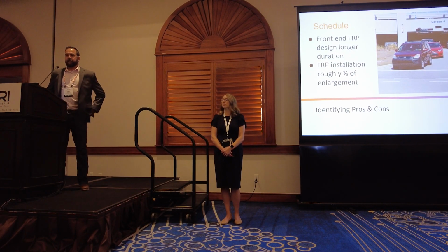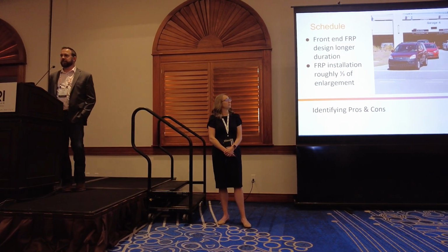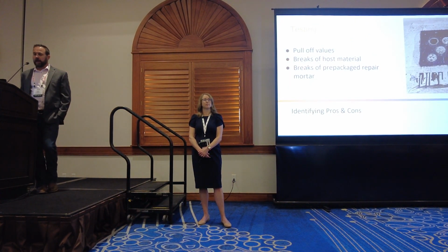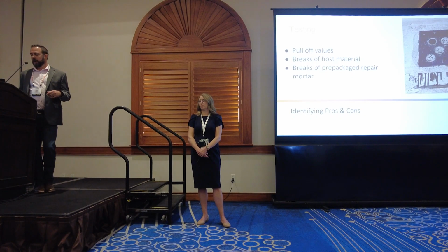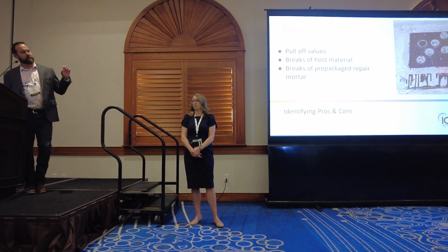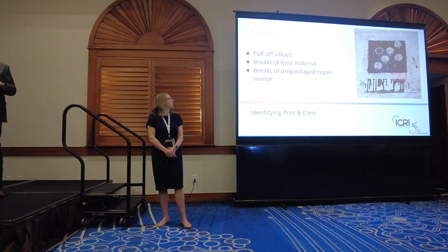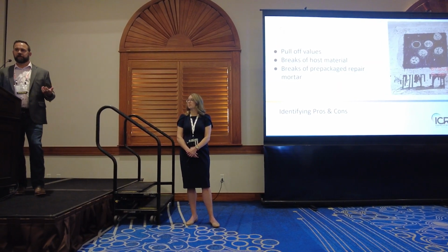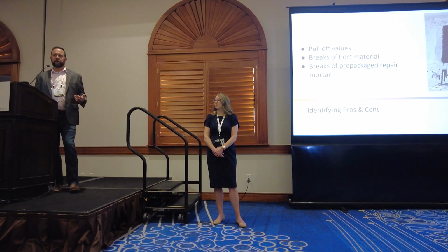This is a perfect example of what this parking garage looked like every day. So as you can tell, schedule is absolutely necessary, and minimal impact to the facility is necessary as well. One of the other major impacts on schedule is testing for the FRP. So I'd like to point out the black circle on the top left. That was actually a failure, but it was a failure because the puck pulled off of the carbon fiber, and we didn't actually get any host material. So it was really a failure between the testing mechanism and the FRP itself. But if you don't have a positive result with host material, then it's absolutely a failure.